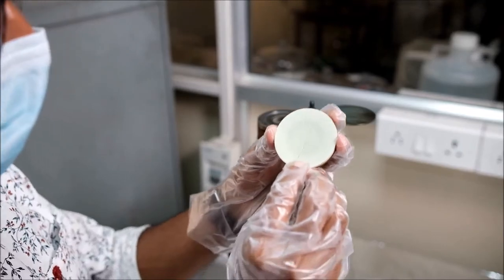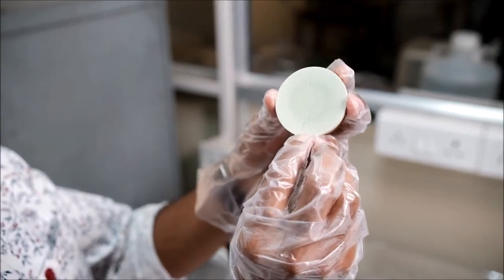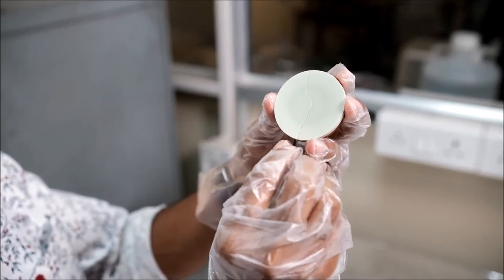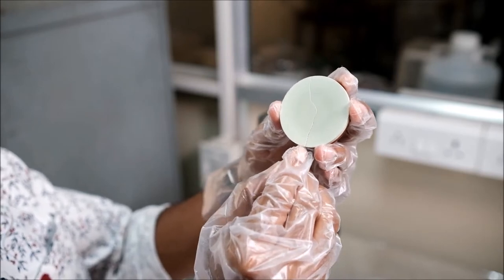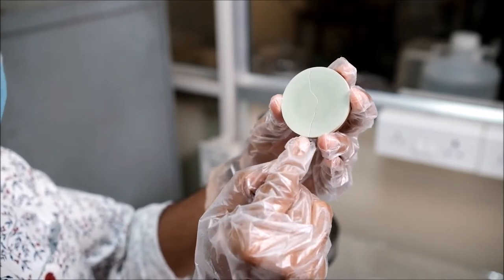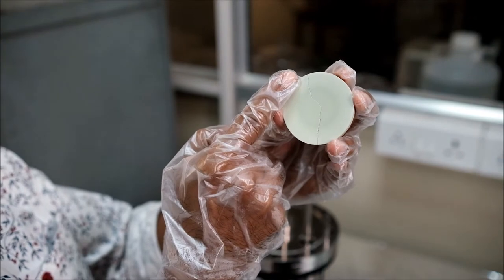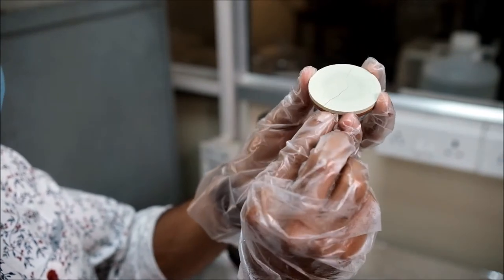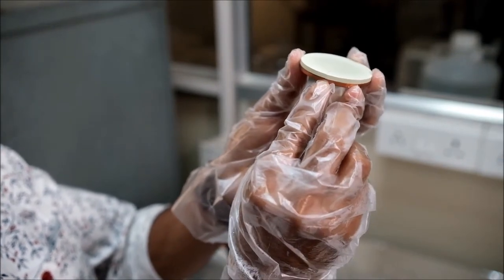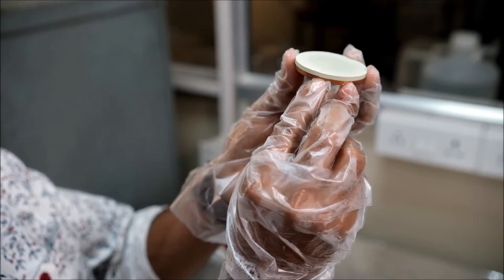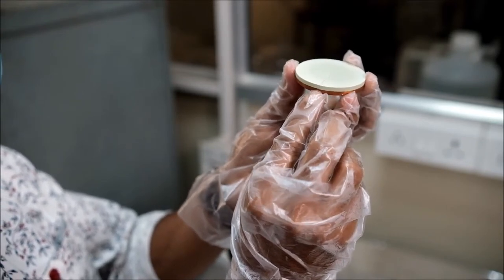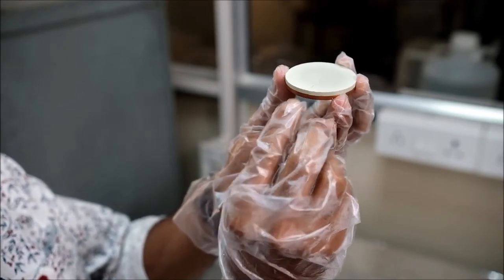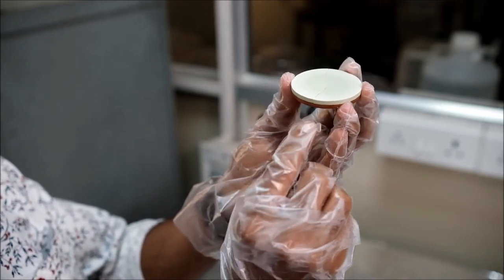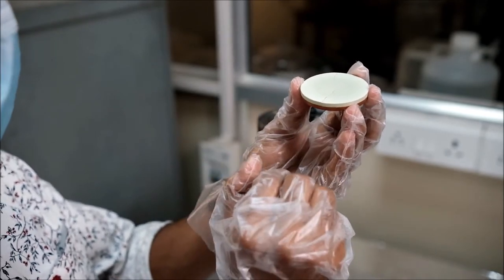You see, this is another tungsten oxide target material, and there is a crack that starts from one end and goes till the other end, and this is completely broken from the surface to the bottom of the target. So this is why heat dissipation is very important for an oxide material, and we have to be very careful while handling this oxide target material.